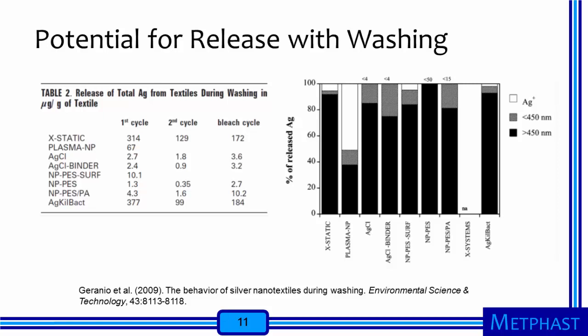For all except one of the test fabrics, most of the released silver was in particles larger than 450 nanometers, suggesting that the applied silver is not really nanosilver, or that the silver particles are agglomerated. The plasma NP fabric was the only one known to use silver particles approximately 100 nanometers in mean diameter. Therefore, it is not surprising that less of its released mass was larger than 450 nanometers.